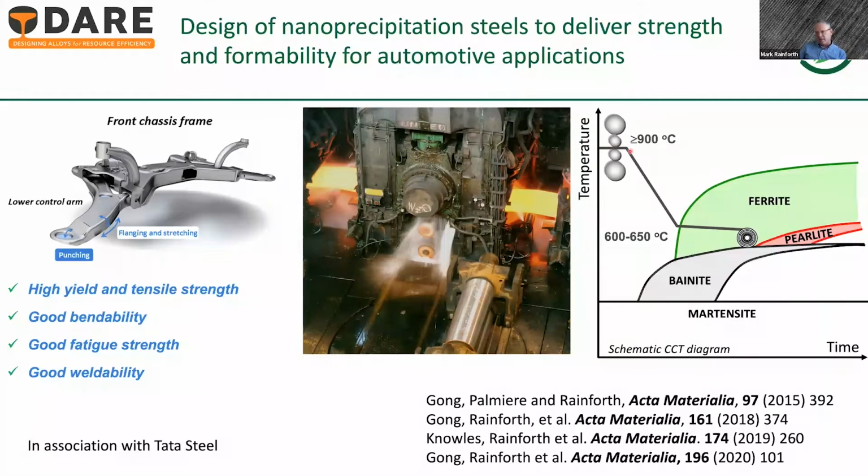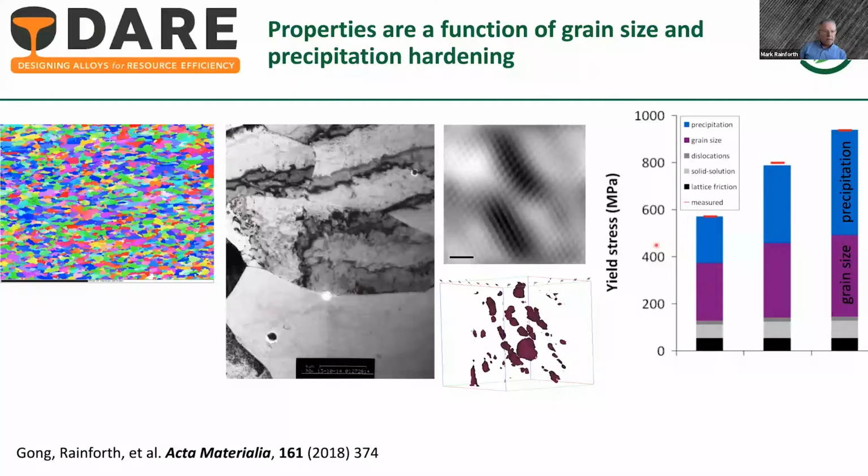And this had to be done on the existing product line, which you can see here. So within the hot rolling temperature range, and then controlled cooling into the coiling range, and then very careful control of that coiling temperature to achieve the final product properties that we wished. This range, again, given us 600 to 650, sounds quite broad. But as with the previous case study, even 5 degrees centigrade change in that temperature had quite dramatic effects on the properties.